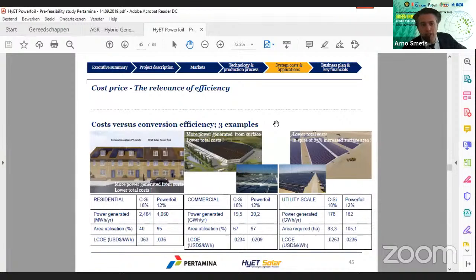Some technologies are more sensitive to temperature effects than others. The thin film I showed is not that sensitive to temperature, so the performance drop is lower than, for instance, crystalline silicon, which also will have some advantages depending on which climate you use. Also the response to the typical spectrum of the sun, depending on the areas, can give performance ratio differences, or the resilience to shading effects. Thin film, with its long stripes of solar cells, is less sensitive to shading in reference to crystalline silicon. So there are a lot of factors in play, but in general, conversion efficiency is defined at standard test conditions: thin film 12%, CIGS 16%, cadmium telluride 17, 18%, crystalline silicon 17 to 20%, best products 22%. And the very fancy, very expensive technologies are above that. Those are the typical conversion ranges.